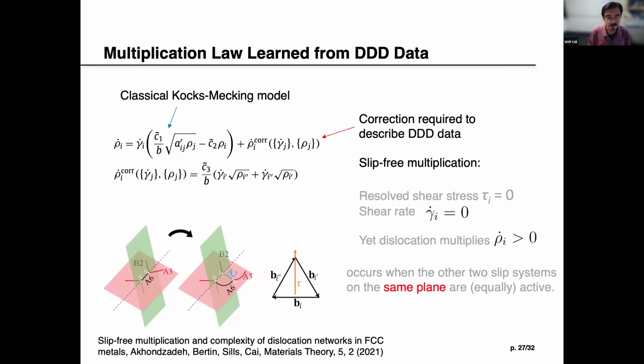And that actually happens quite a lot, so we call it slip-free multiplication. In order to describe that, you have to add a correction term, right? If there's time, I can go into more detail about that. The DDD data suggests that, and then we go back and find the mechanism that's causing that.